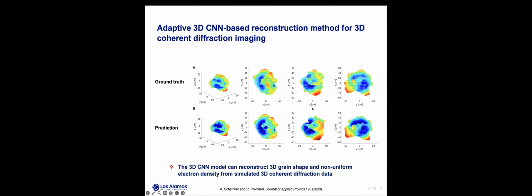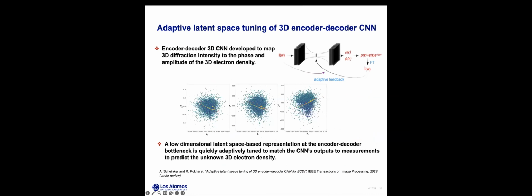these crystals. So in the next example of adaptive ML, we developed an encoder-decoder type 3D CNN to map this 3D diffraction pattern or intensity to the phase and amplitude of the 3D electron density. In this case, the diffraction patterns are represented as low dimensional objects in the latent space, which is the bottleneck in the encoder-decoder architecture, and this latent space is then adaptively tuned using this extremum seeking method, allowing us to improve the predictions of our work.